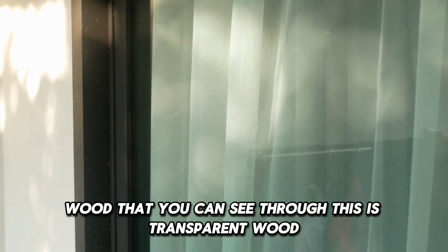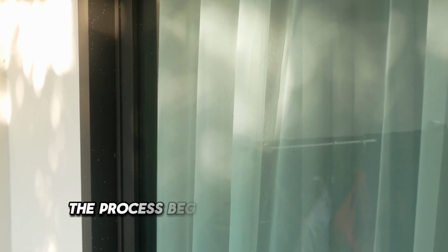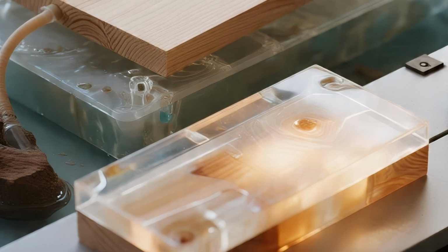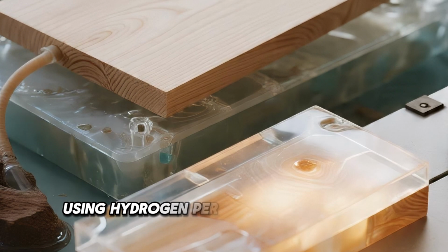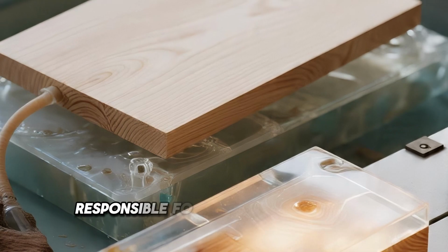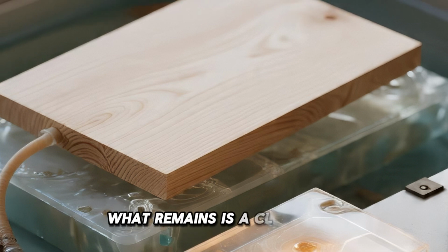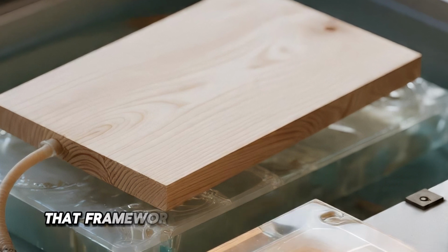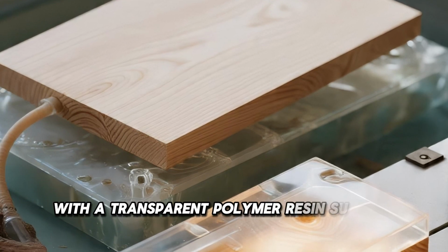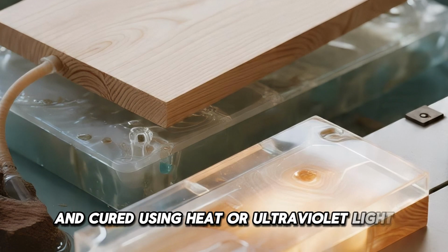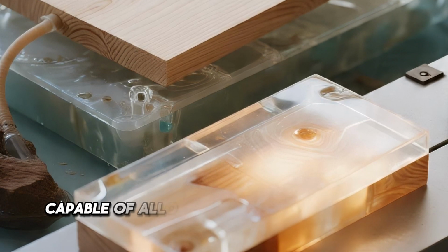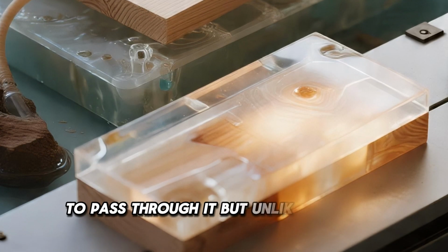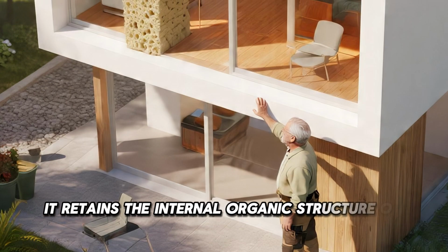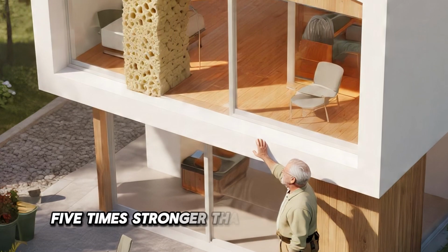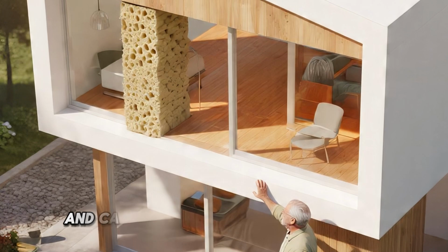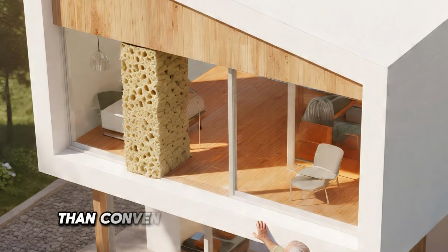This is transparent wood. First developed at the University of Maryland, the process begins with thin sheets of natural wood, such as balsa. Those sheets are treated in a chemical bath using hydrogen peroxide to remove the lignin, the compound responsible for much of the wood's natural color. What remains is a clean, pale, hollow cellulose framework. That framework is then vacuum impregnated with a transparent polymer resin, such as epoxy, and cured using heat or ultraviolet light. The result is a sheet of translucent wood capable of allowing up to 90% of natural light to pass through it. But unlike ordinary glass, it retains the internal organic structure of wood. That structure makes the material 5 times stronger than traditional glass, far more resistant to shattering, and capable of providing dramatically better thermal insulation than conventional double-pane windows.